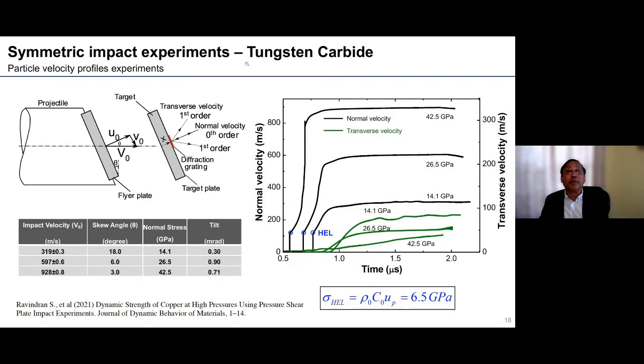These are the symmetric impact experiments on tungsten carbide, and here I show you velocities ranging from 300 meters per second to 900 meters per second. The normal stress, or nominal pressure, ranges from about 15 GPa to about 42 GPa. Here we show you the normal velocity and the transverse velocity. The transverse velocity, in green, is just tungsten carbide on tungsten carbide, both the normal and the transverse velocity. As you can see, we can clearly observe the HEL, the Hugoniot elastic limit, which in this case is about 6.5 GPa. Then we can see the elastic plastic shock, which is steepening as the pressure increases, and then you see the shock state, which goes from 14 to 42 GPa. The transverse velocity is plotted here.